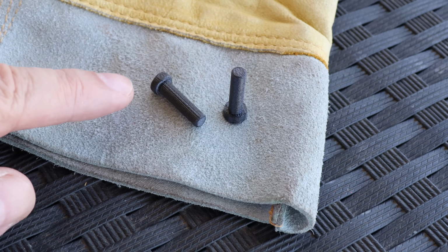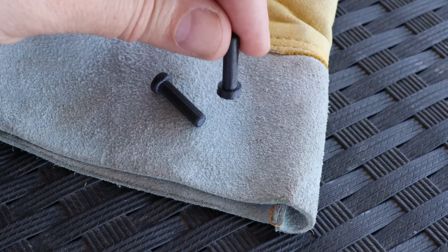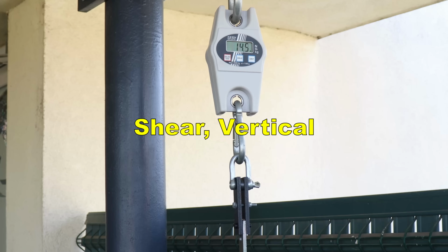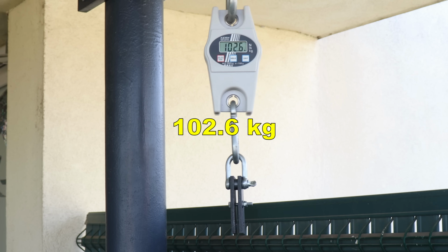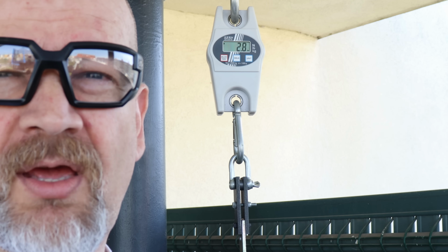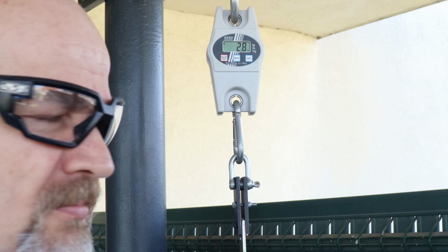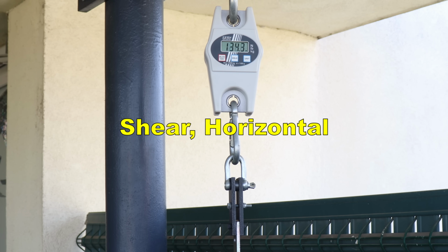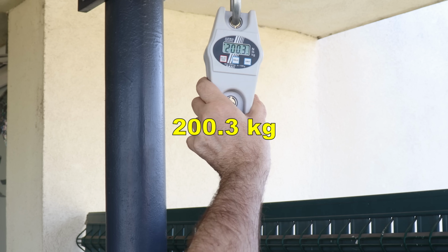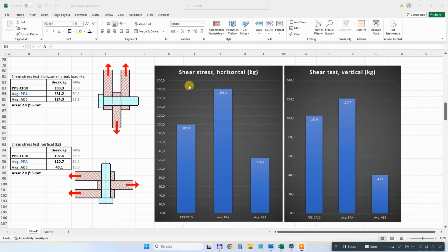Shear test with horizontal and vertically printed test objects, and I'm starting with these ones because the load is smaller. And now printed in horizontal position, and I don't know what to expect here. With PPS, this equipment is not enough because the maximum here is 200 kilograms approximately. Let's try. On the edge. Printed in horizontal position, it is quite strong, but it is between these two materials. Printed vertically, it is very close to the PPA because of that good layer adhesion.